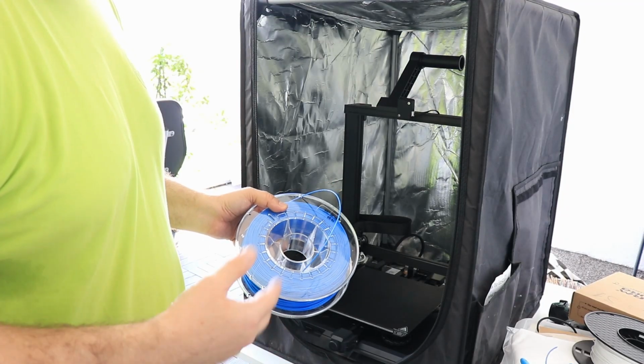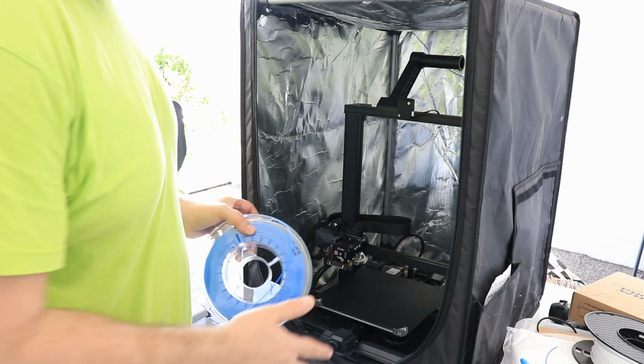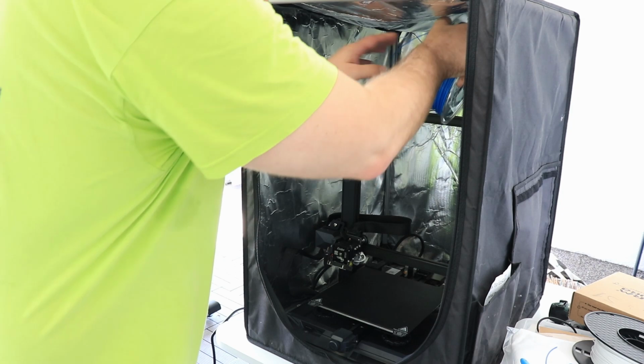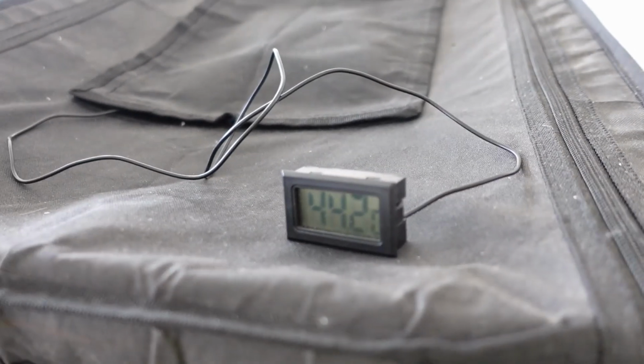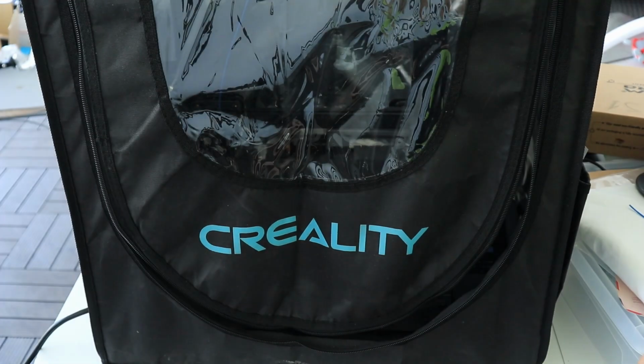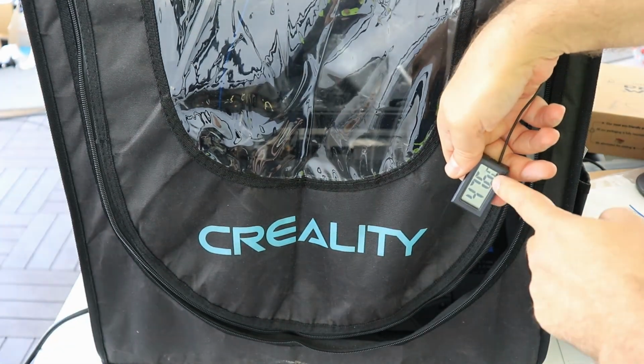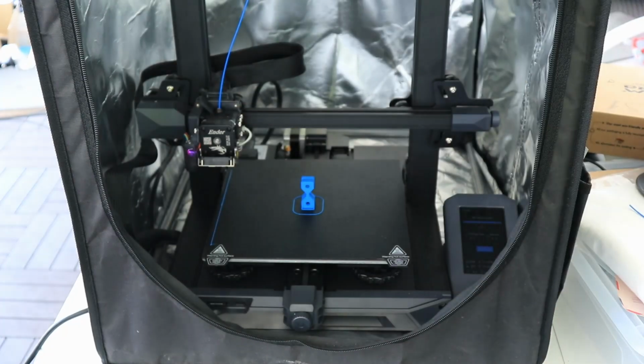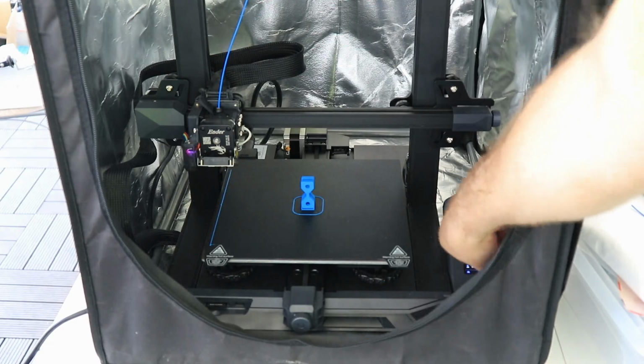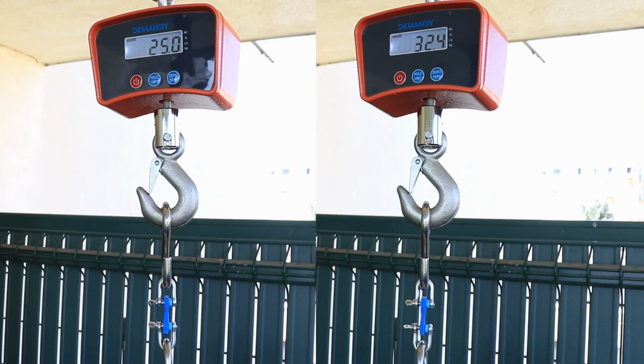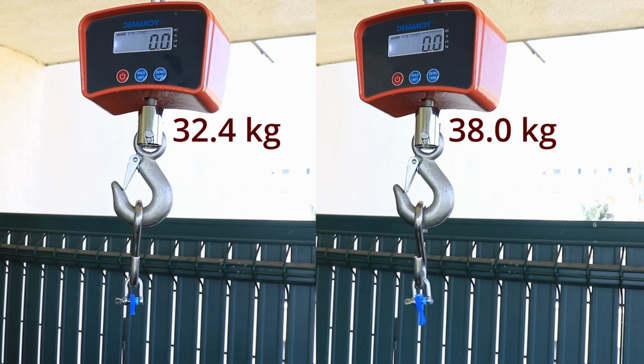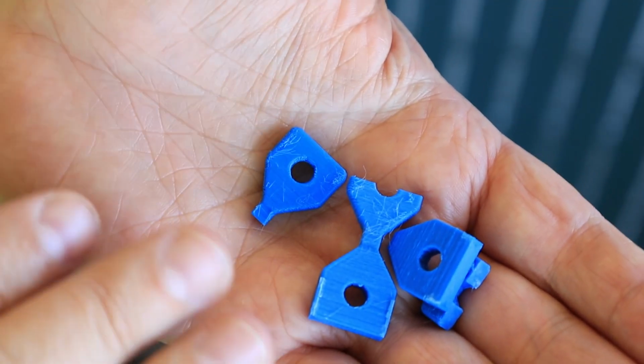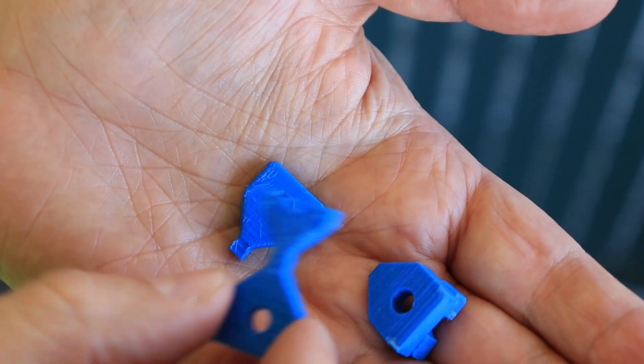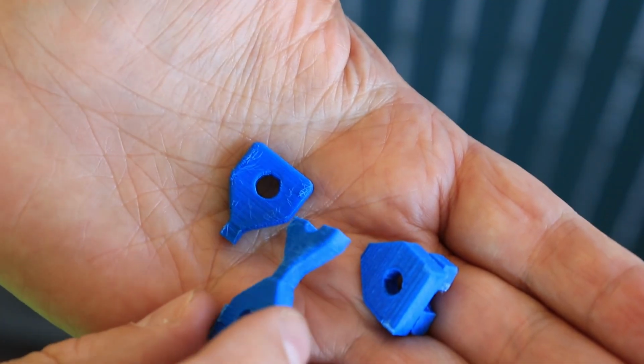Now, that layer adhesion test I want to repeat with test object printed inside the enclosure using the same parameters. It's a little bit hard to see, but after approximately 20 minutes the temperature inside the enclosure is 44 degrees Celsius. The printing is finished and the temperature went up to 47.7 degrees Celsius. And repeated layer adhesion test with objects printed inside the enclosure. Well, at this moment I don't know the numbers, but even for the feeling this was much stronger, but one test subject didn't even break on that smaller cross-section area.